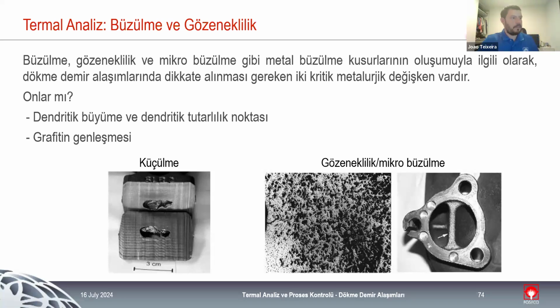liquid metal. And one way that we can control this is with thermal analysis as well. It's a good indication, and it's a good tool to study the dendritic growth and the expansion of graphite, and of course the careful use of feeders in the casts, especially the big casts. We need to be extra careful with the position of the feeders in production. For example, when you cut them, they always should have a shrinkage inside. If they don't have a shrinkage inside, it means that the shrinkage is most likely inside the cast, or the position of the feeder is not correct, and we should move it.